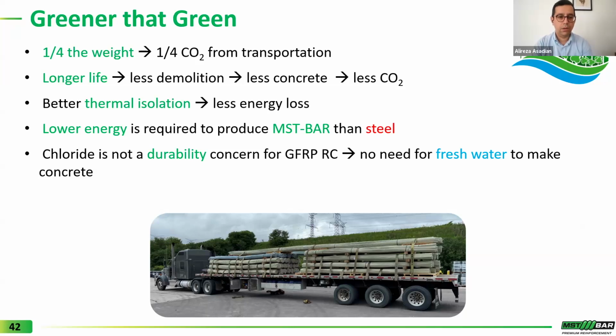GFRP bars will have longer life, so less demolishing of existing structures, less energy used to recycle those structures, less concrete used to build new ones, and all in all, less CO2 emission. GFRP reinforced concrete elements will be better thermal insulators because GFRP bars are not thermally conductive, and therefore there is less energy loss in buildings reinforced with GFRP bars. Also, very important to know that lower energy is required to produce MST bar than a steel rebar, and we'll talk about this point in my next slide.